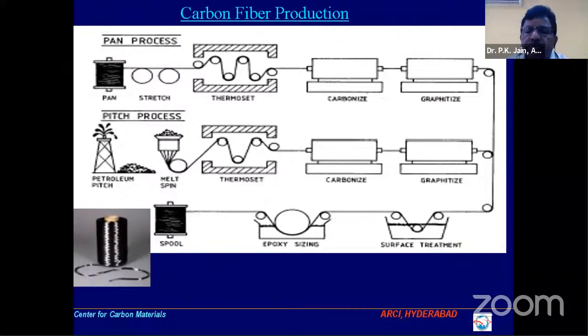But since carbon has a neutral surface, it does not react. So commercially, the carbon fiber is given a surface treatment for introducing surface groups, so that it becomes a very strong interface. And then these are the tows, which have many filaments, sometimes 12,000 filaments in a single tow, or 3,000 to 10,000, 12,000 is very common. So it is given an epoxy sizing to handle. Now whatever you see, this is a commercial grade carbon fiber. In this tow, around 3,000 filaments are there in a single tow.